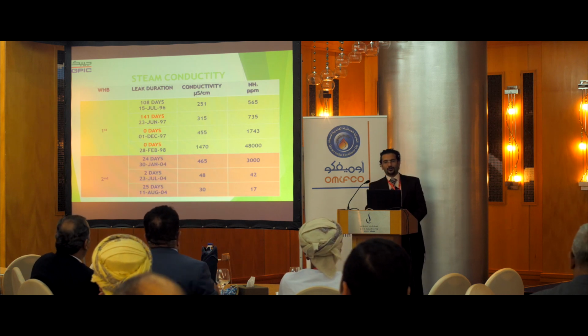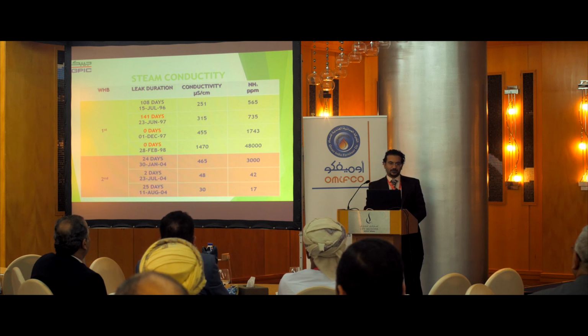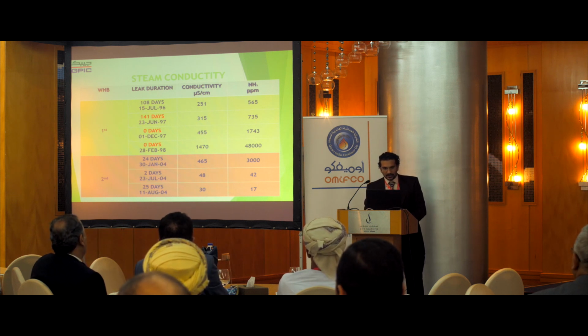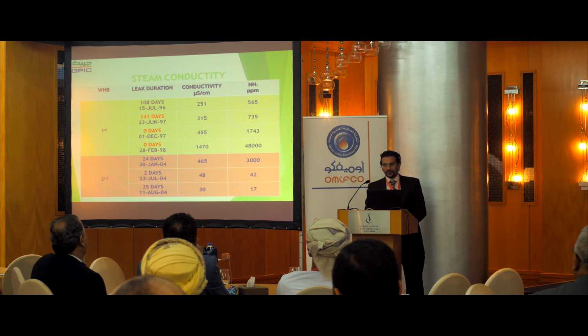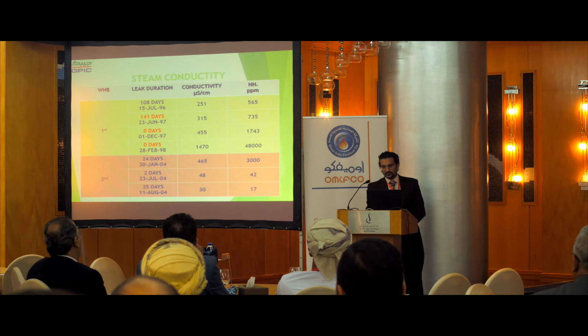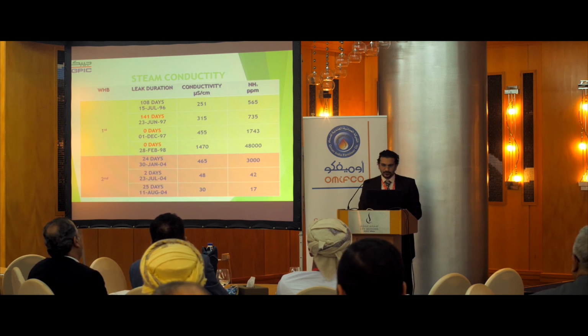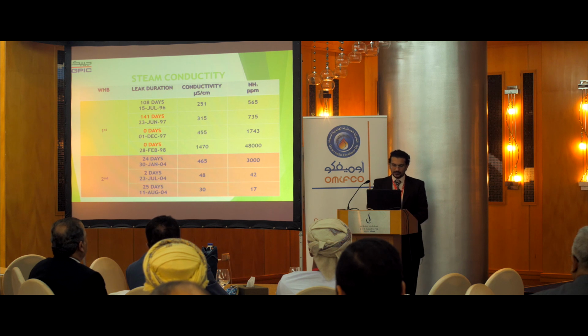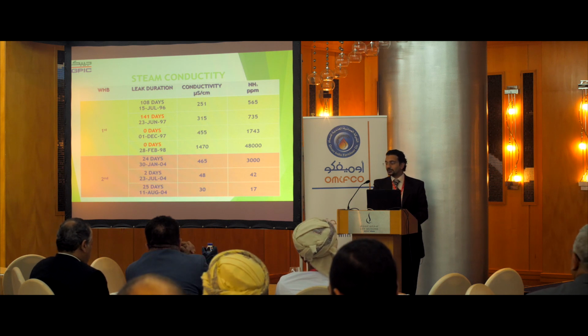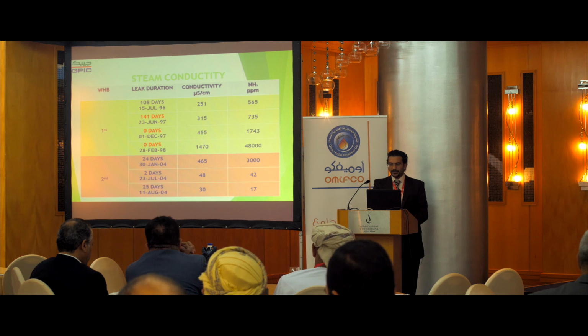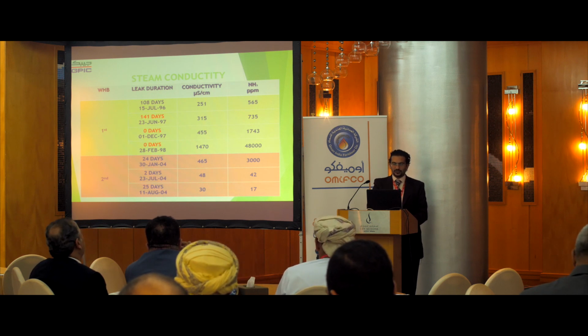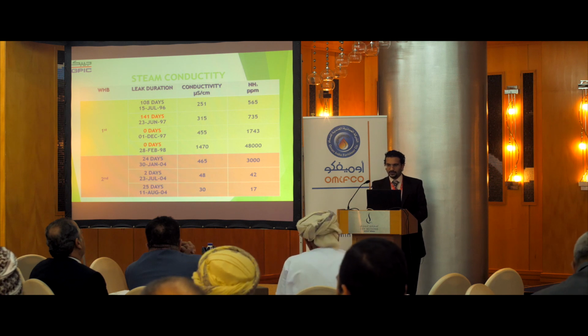This is just a record of the steam conductivity when we got the leaks of the waste heat boiler. So our Bellelli boiler: the leak duration was 108 days. Our conductivity was 251, and ammonia went 565. And then by the end, on 28 February 98, conductivity reached 1470, 48,000 ppm ammonia. And our second waste heat boiler, our first leak, 465 microsiemens per centimeter, and then ammonia 3,000. And finally, when we replaced it, after taking our measures, conductivity was 30 and ammonia ppm was 17.